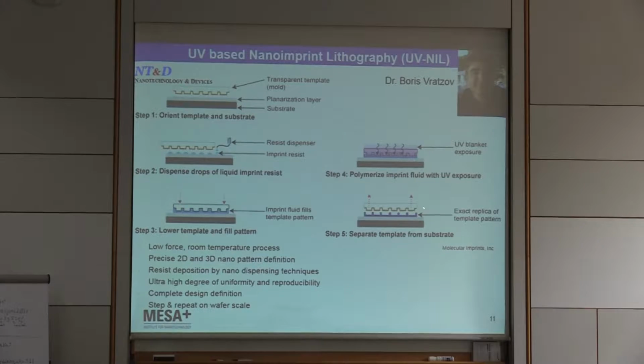Now you have these features. You have the residual resist layer. So you could think of now doing an etching step, an oxygen plasma, for example, to remove this residual layer. So the protrusions will stick. They will be reduced a little bit in height, but you will expose the substrate. And after that, you can do standard metallization and lift off, or you can use this resist as an etch mask and etch.